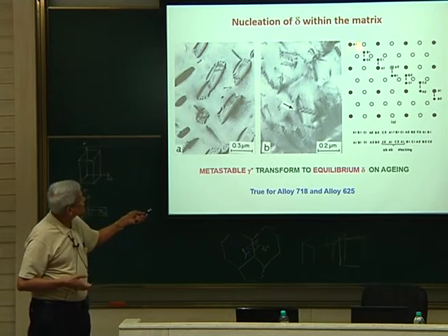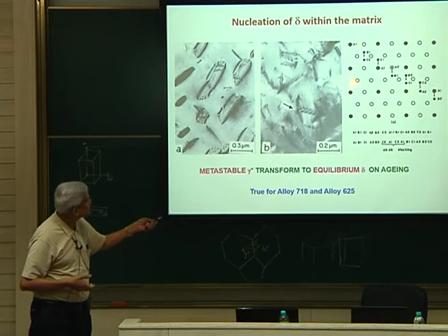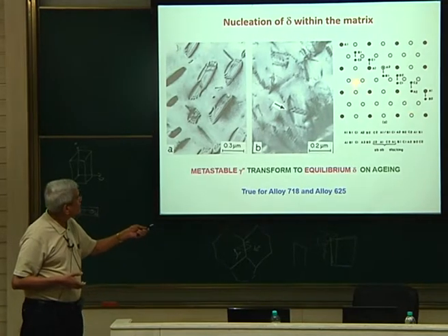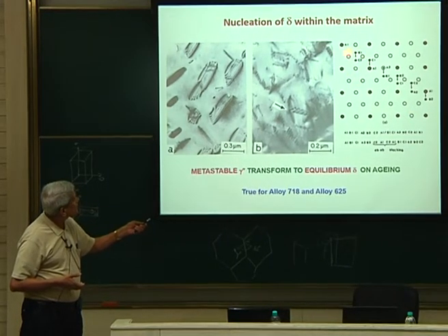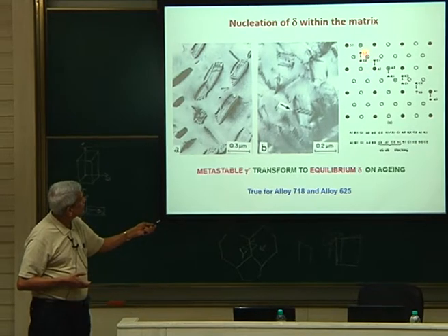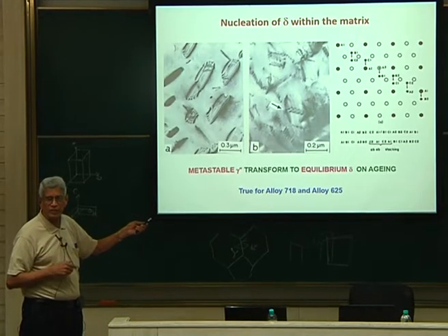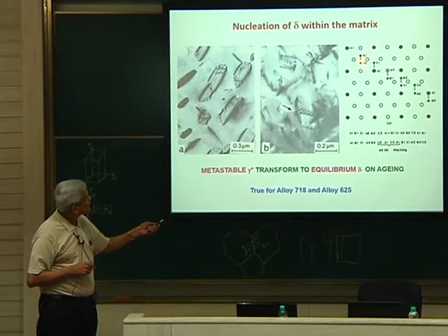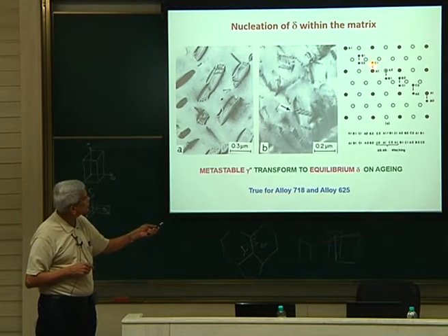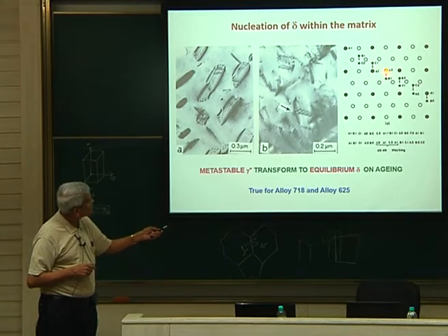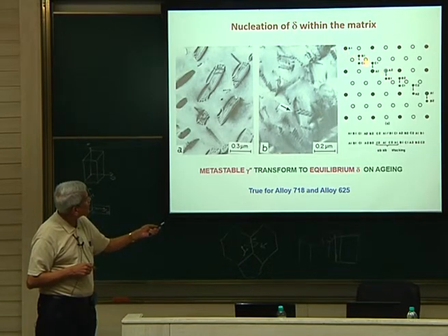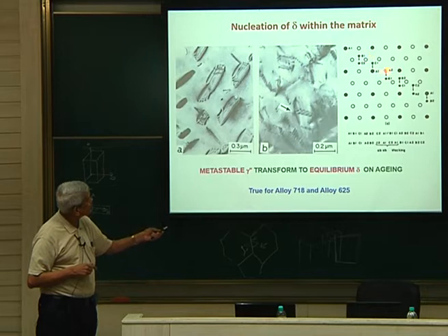And this is how the stacking sequence changes, which is being shown for an FCC. Here also the same thing is being done. If you look at it, this is a layer, then the B layer atom will be moved from here to here by a 1/6 <112> partial, which creates a stacking fault in FCC. Then the next atom, which is on a position which will come here, is moved from here to this position. The next atom, when we consider it, should have been, according to the stacking sequence, an atom represented by an open circle. That's nothing but a nickel atom here.